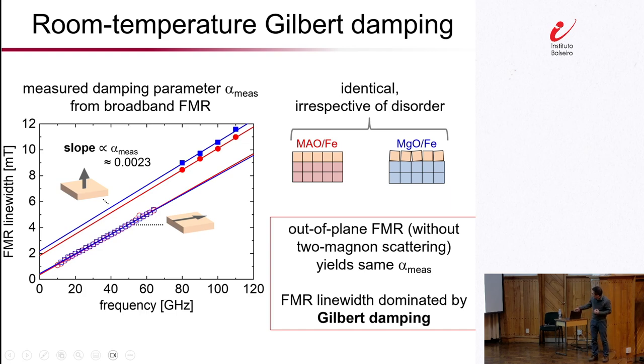Now, some of you in the audience might be wondering about the notable difference in the vertical intercept. We can attribute that to the amount of magnetic inhomogeneity. There is a pretty well-established conventional wisdom in the field that the vertical intercept is related to what we call inhomogeneous broadening, again borrowing the language from NMR. The funny thing is that we tend to see more of this inhomogeneous broadening even though we are looking at the same material. But at this point, we believe that this is somehow related to the different shapes of precessional orbit in the magnetic film.